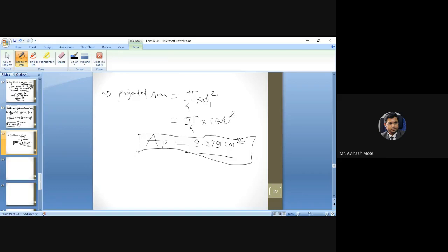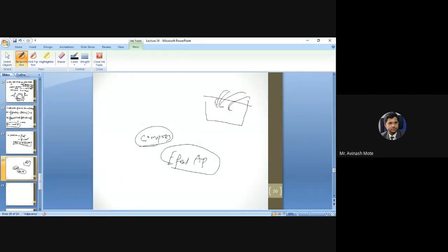So projected area must be considered for all the cavities available. In compression molding, for calculating the pressure we considered only the effective projected area, because we just put the material inside the cavity and compress it with the ram or some other mechanism.